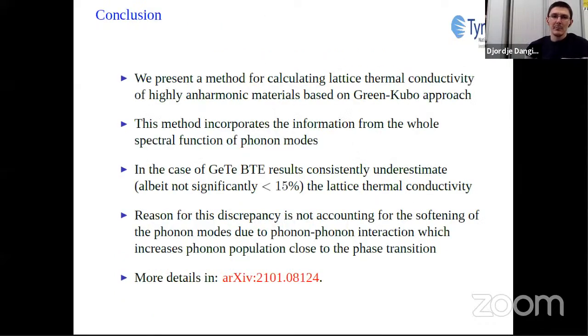In the end, I'm concluding by saying that we presented a method for calculating lattice thermal conductivity of highly anharmonic materials based on the Green-Kubo approach. This method incorporates information from the entire spectral function of phonon modes. In the case of germanium telluride, the Boltzmann transport equation underestimates the lattice thermal conductivity compared to the Green-Kubo approach. The reason for the increase of the lattice thermal conductivity in the Green-Kubo approach with respect to the Boltzmann transport equation is the increase of the phonon populations due to phonon-phonon interaction.